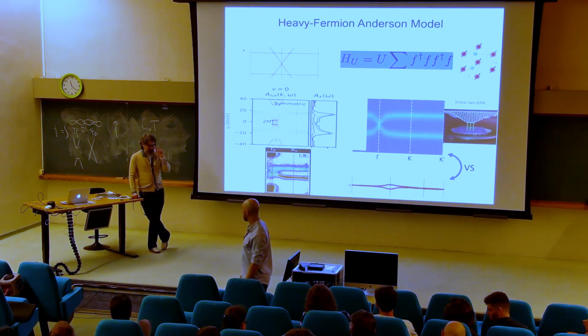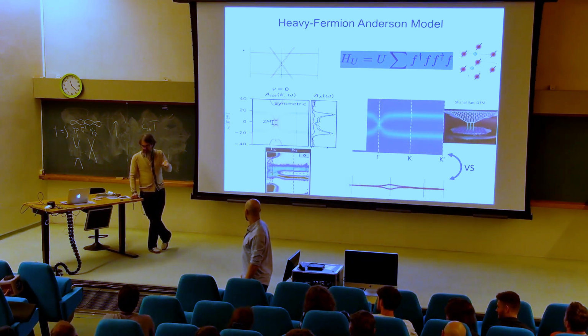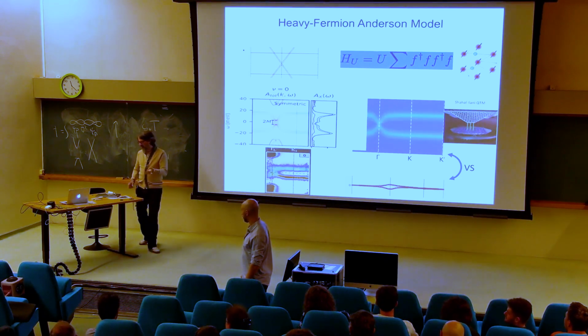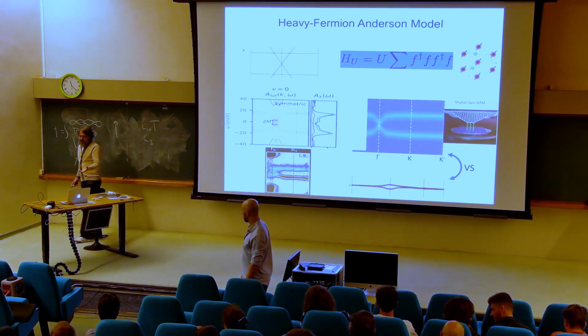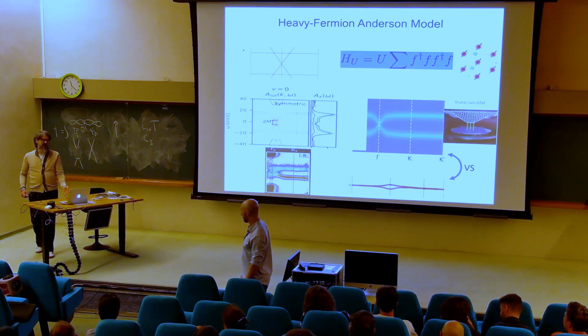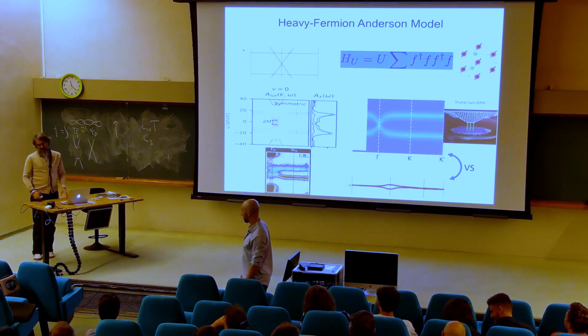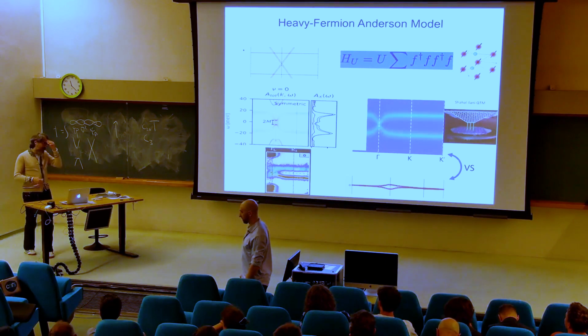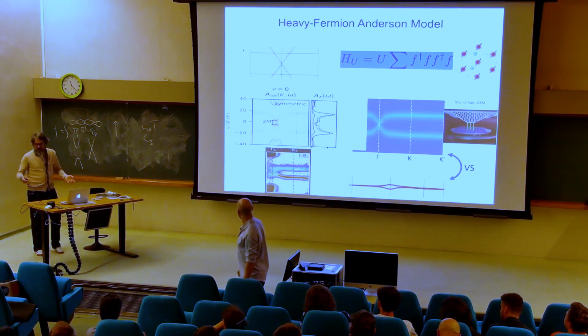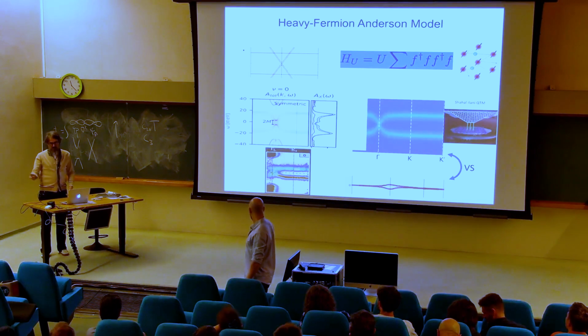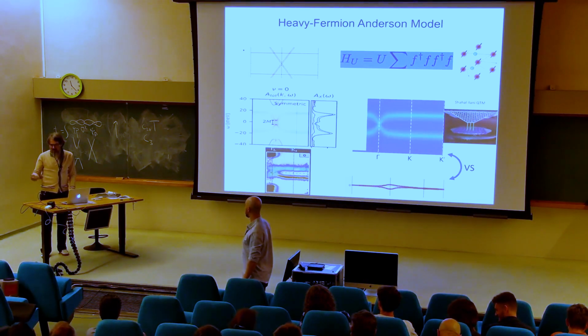And it tells you that most of it is gapless, in the sense that some people, like Stefan, see a transition between gapless and gapped, whereas Ali sees gapless. I think Andrei also sees gapless. So let's say it's gapless and spin triplet. You can get this with the heavy-fermion theory. You can get this to be the lowest state. Now, as you know, there's many other states that are very competitive. For example, in some limit, this system has some U4 symmetry, which makes a lot of the gapless states have the same energy.